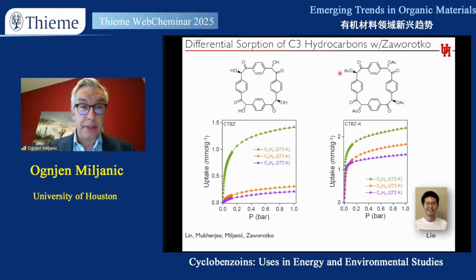The other feature that facilitates selectivity is that the pores are relatively rigid. So if you do molecular dynamic simulation of them, there is some oscillation that you see, but the pores mostly maintain their shape throughout the simulation. In contrast, the acetylated molecule, because these pores are not held together by hydrogen bonding, but simply by the awkward shape, if you watch this video, it looks very sort of peristaltic, in that those wiggly pores are able to kind of push through the guest into the material, even though the guest may not be a perfect match. And so this really highlights the shape and the flexibility of pores.